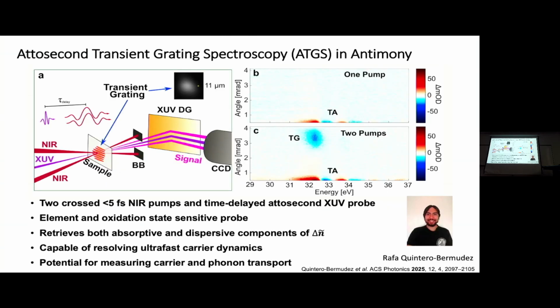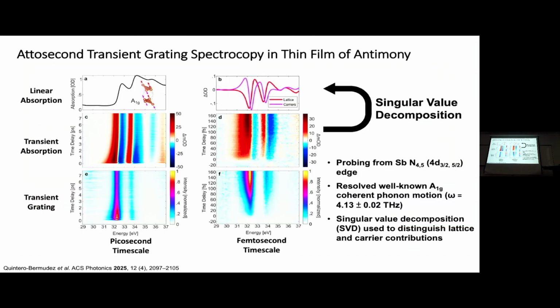So Rafa built up a setup in our group to do this. Write the grating, diffract it. So here's the diffracted beams. Here's the normal transient absorption on axis. This is the energy of the XUV photon. Here's the transient grating, the diffracted signal. If you block one of the lasers, the diffraction goes away. So you know immediately, you just put a card in and the diffraction goes away, you know you've made the transient grating. And this was done in antimony, which has a really great coherent phonon oscillation.